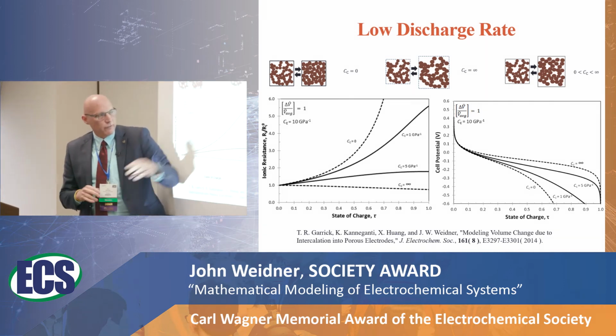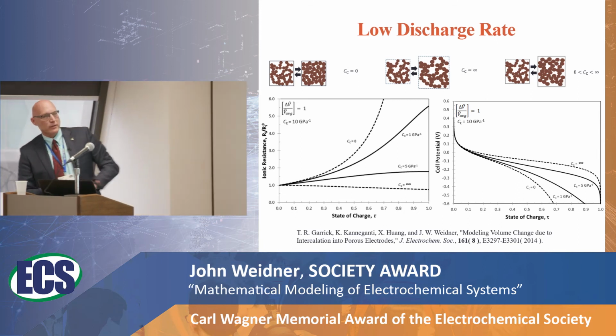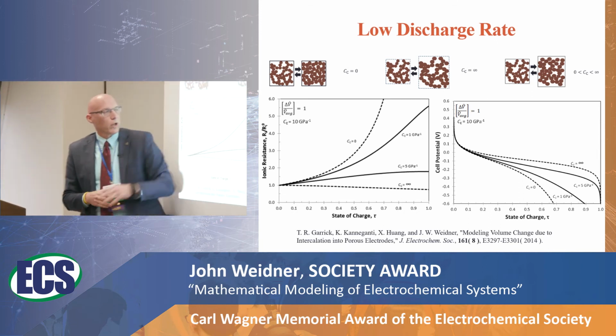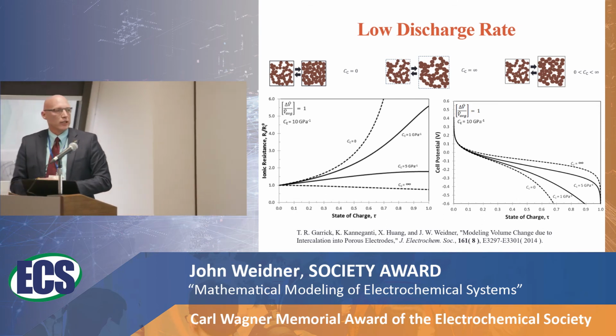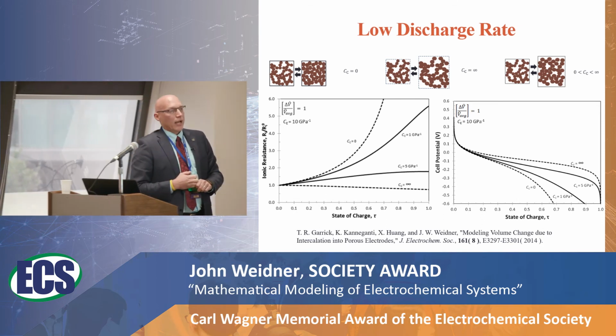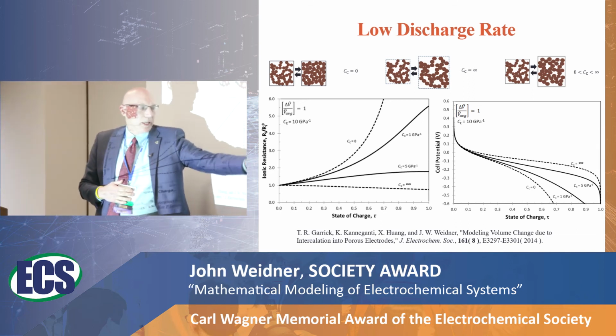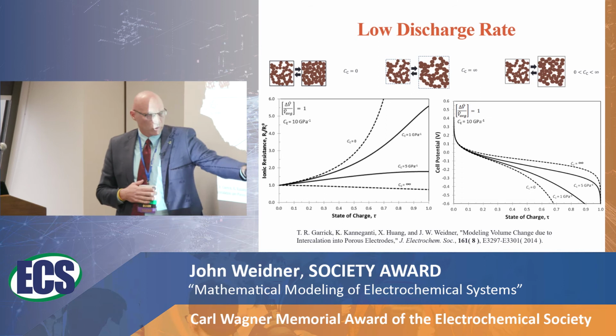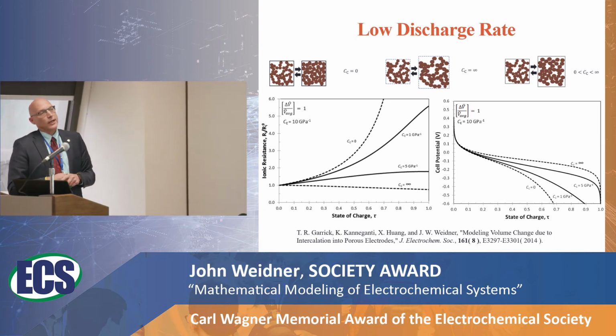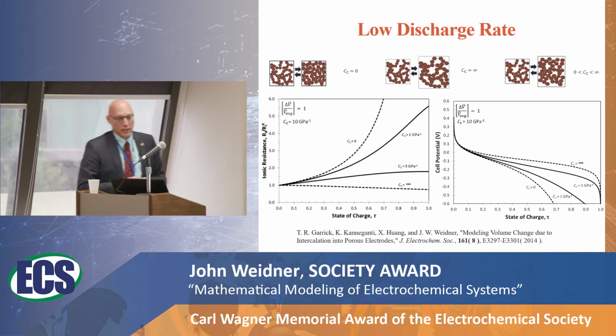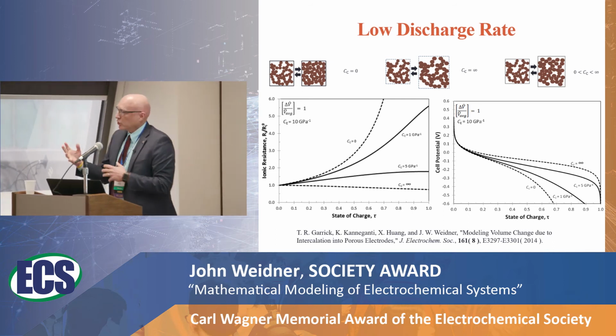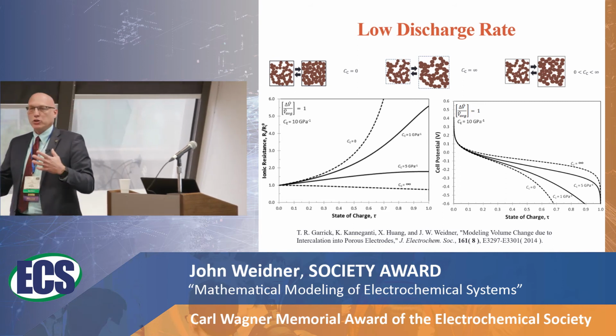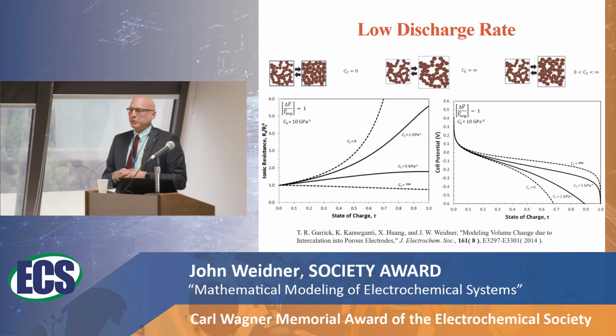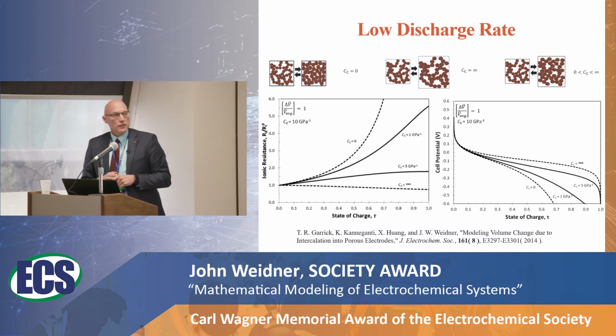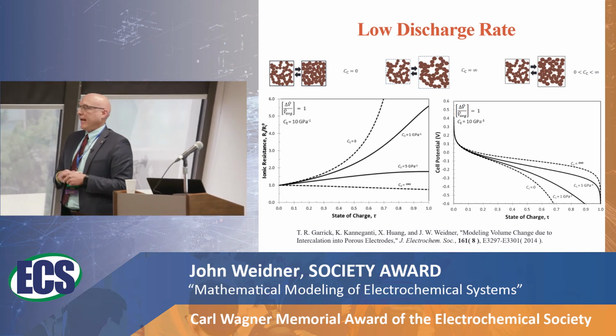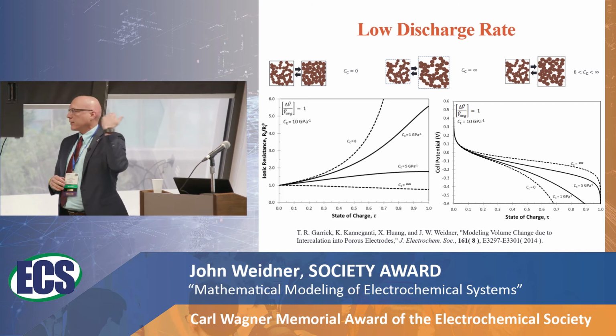So here's, again, a fictitious one-electrode battery. We're just seeing what it's doing relative to a zero point with a Nernstian equilibrium potential. And when most of it goes into porosity changes, the resistance goes up exponentially and the voltage drops off fast. If there's no resistance, you just have a nice Nernstian relationship between the two. So that gave us some insight. It also showed us the importance of properly capturing the porosity change. But now we want to put it in an actual battery.